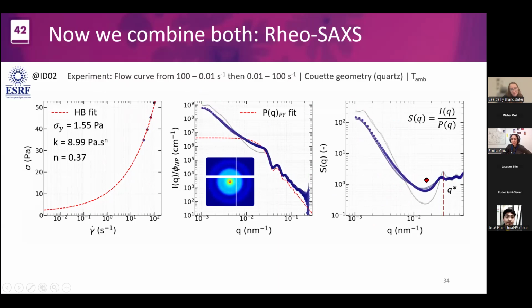We go from high shear rates, and here our structure factor peak is very flat. What is that telling us already? It's telling us that the probability of being close at that characteristic length scale is becoming lower, but that's not the whole story, because you can also look at this part of the curve, and what you see is that the mass of a scattering object at this length scale has remained. It's not completely flat like in the case of when there's just one particle here. So the particles are not just fully decorrelated from each other. There's still a structure. It's just that during flow, something is happening in the density of that pocket, actually.